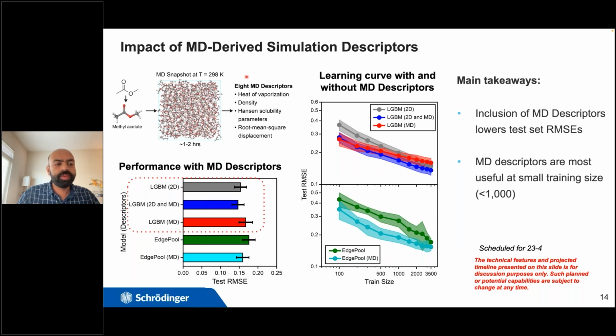And we use these descriptors in combination with the 2D descriptors. For example, you can see here on the bottom left, we use the light gradient boosting machine algorithm with 2D descriptors. Then we also use the light gradient boosting machine with 2D descriptors and MD descriptors. And we use a graph-based method called EdgePool without any descriptors, and EdgePool with MD descriptors. So what we see is that adding MD descriptors, especially in the low dataset regime, really improves the performance of the model.